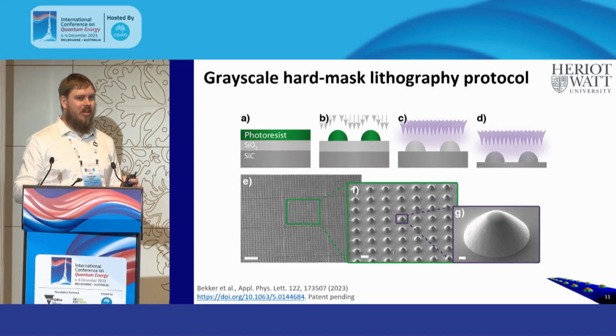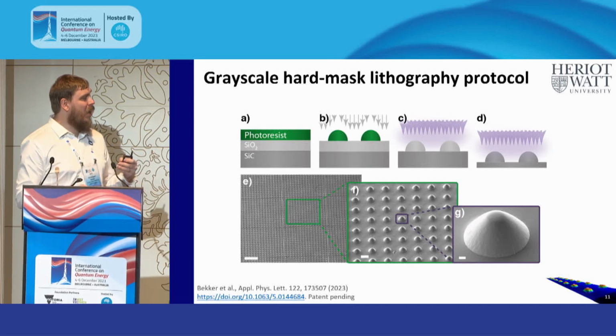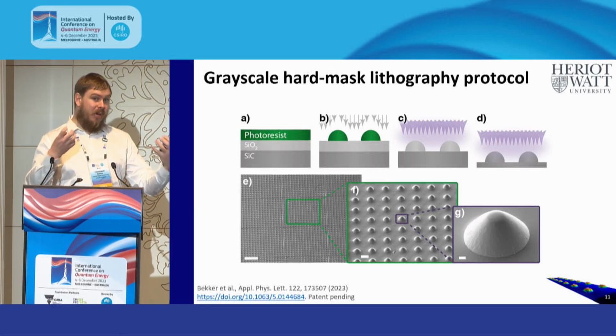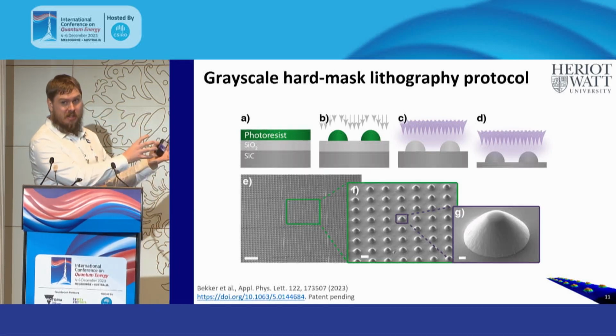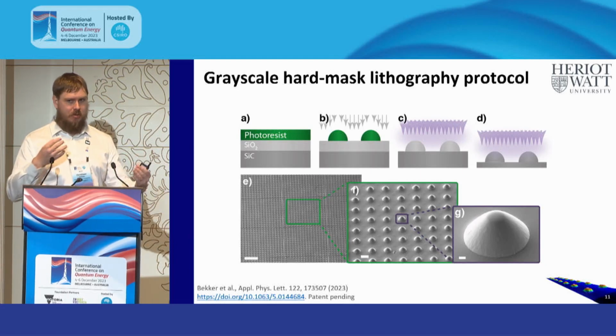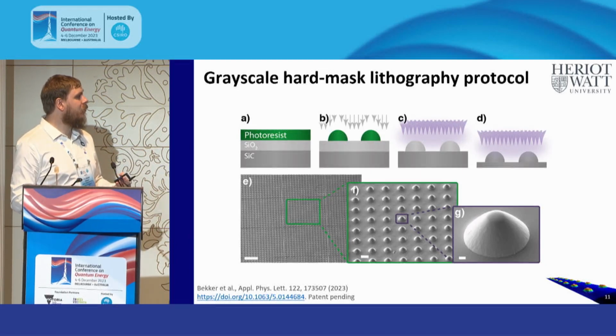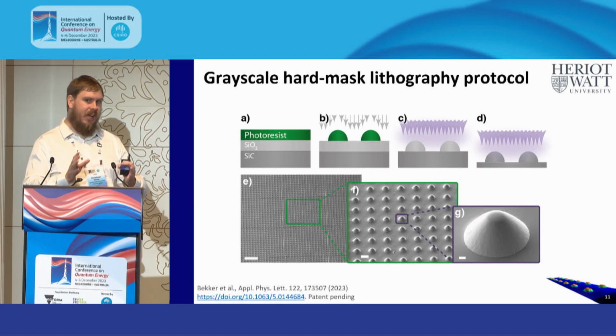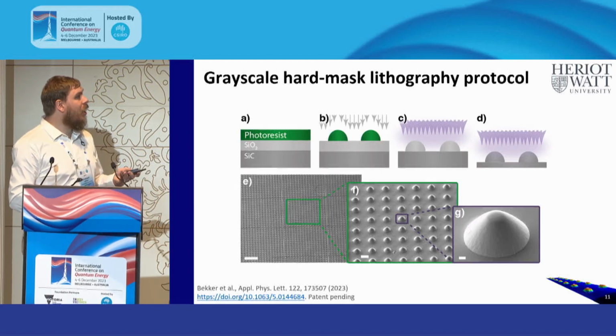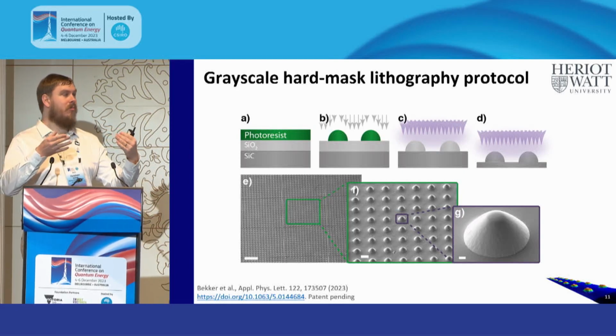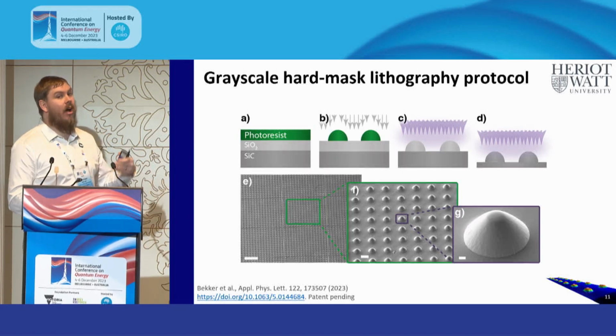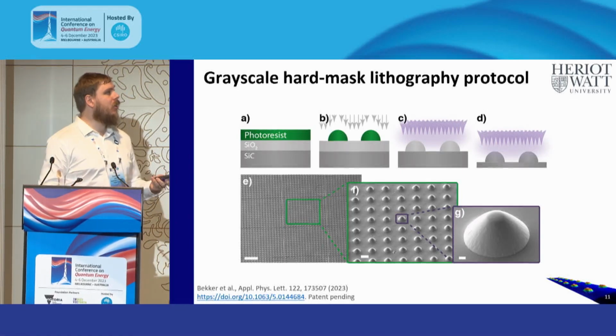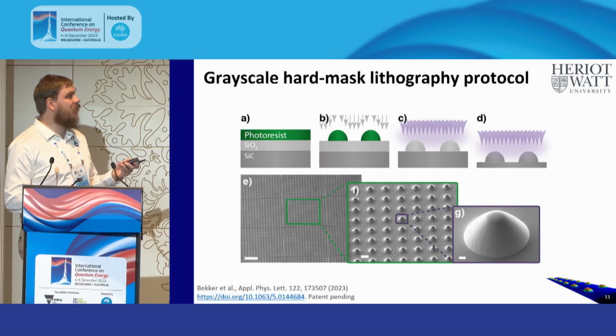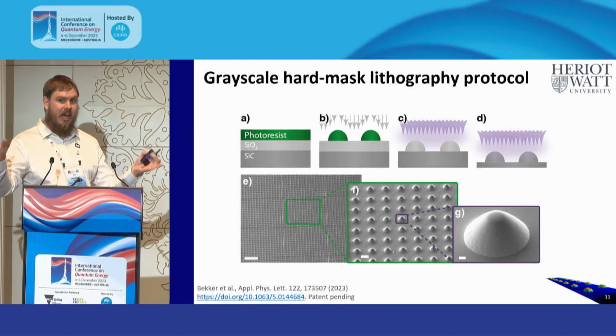And by having two etch steps, we do more than just add complication to our system. We actually give ourselves the ability to separate the two processes, the process of working with our resist and working with our substrate, in terms of chemistries, in terms of etch process, in terms of difficulty to etch. I should also mention that we use reactive ion etching, just in passing, so a dry etch method that's anisotropic, so it etches straight down. And we also give ourselves the possibility of tuning and selecting, for example, how selective our etch is. So how high do we want our final shapes to be, almost like after the point of developing our resist and creating our shapes.